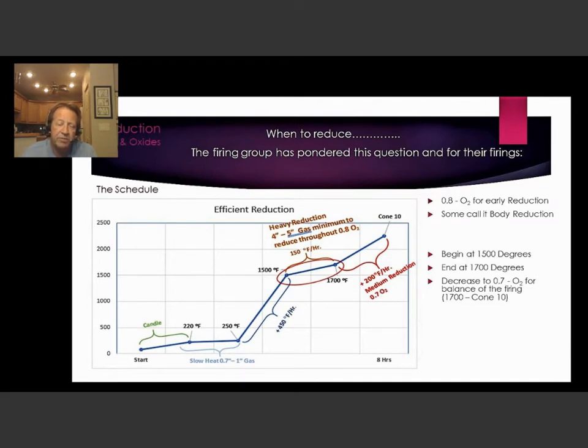Their heavy reduction, they've figured out for their kiln to minimize the infiltration of air or oxygen. They need to go into this heavy reduction period at a minimum of 4 to 5 inches of gas, for lack of a better description, to fill their kiln so they don't have any dead spots. After 1700 degrees, they decrease their O2 level to 0.7 for the balance of the firing, and that is almost always from 1700 degrees on up to cone 10, because that's what they fire.